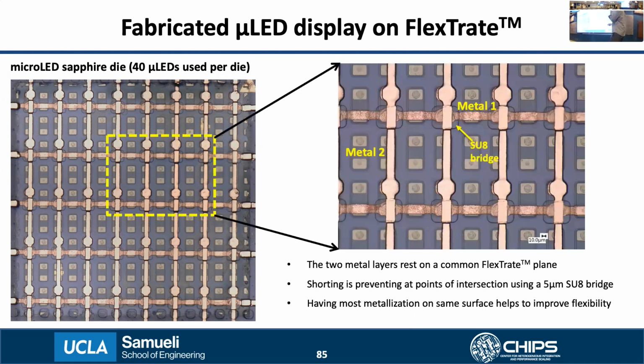If you further zoom into the metal layers, you can see how the two metal lines have been fabricated. The horizontal lines which short the P contacts connect to the voltage IC, and then the vertical interconnects connect to the current IC. The way the two lines have been fabricated is that in all those regions where the metal lines don't overlap, they lie on the same level of FlexTrate. However, where the two interconnects crisscross or meet, there is a 5-micron thick bridge of SU8, which separates them to prevent them from shorting.